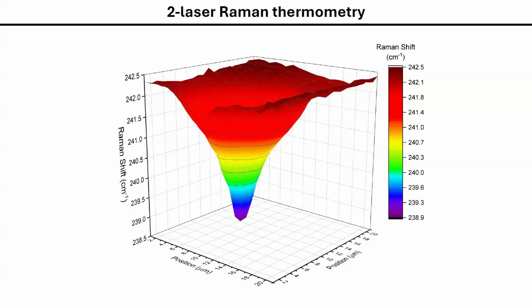Yes, of course, there are many ways to estimate the temperature from Raman measurements. However, this setup, the setup of SL back in the days, was optimized to measure shifts. It had very high resolution on the frequency of this mode and not so much on the intensity of this mode. Also, if you want to look at the intensity ratios of the Stokes and anti-Stokes, which is related to the phonon population and so to the temperature, you need to have less resolution as well. You need to look at a wider window. So this setup is precisely designed to measure shifts.